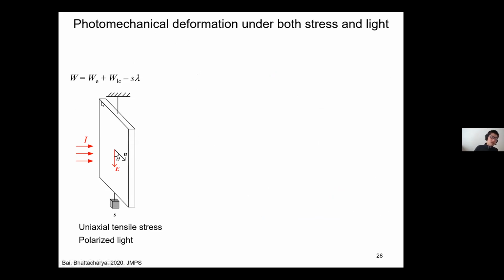So we have a simple problem here we want to study. We have a thin sheet. We don't need to worry about the propagation of light in the material. We assume it's thin enough. The light intensity is homogeneous. And then we have a prescribed uniaxial stress load, and then I shine a polarized light in a certain direction. In this case, the polarization is along the tensile stress. Okay, it's the same direction. And I want to determine the deformation, but then I also want to determine actually the nematic director in this material. This is not fixed, but this needs to be